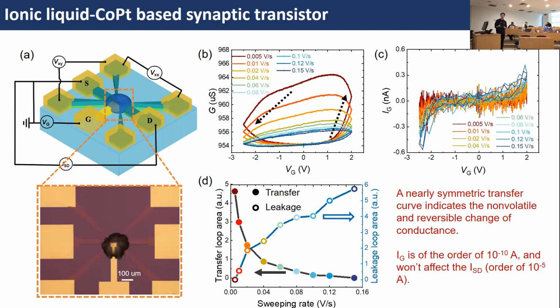And here we use a CoPt film. The CoPt film can use the ionic liquid as the electrolyte. We first sweep the gate voltage anti-clockwise at different steps. And here we can find that there is a huge hysteresis loop. It means that ions are being trapped in the channel, and the leakage current here is quite small, less than 1 nanoampere. So it means that this device can trap the ions in the CoPt film, and in this way, it can work as a synaptic transistor. It has the potential.